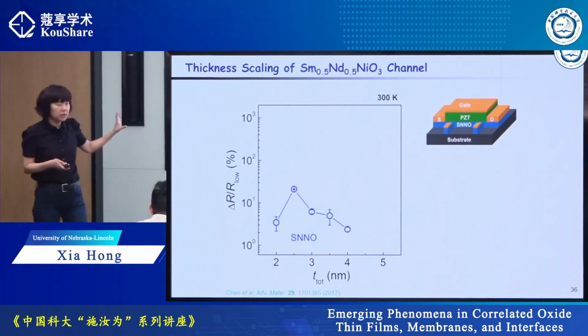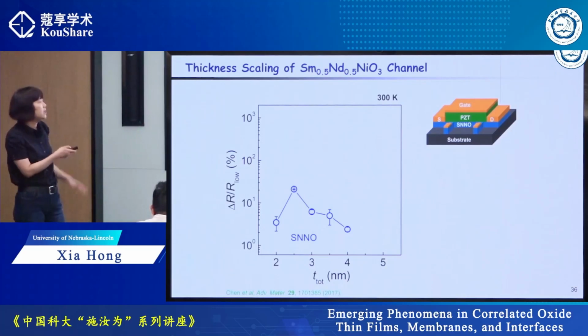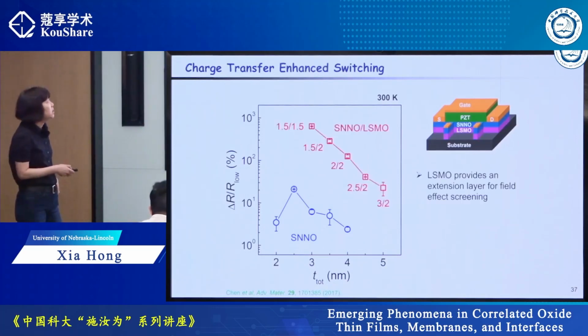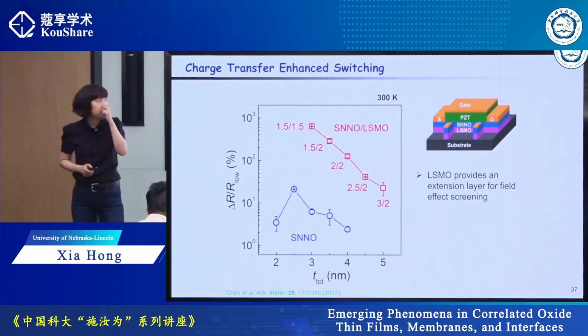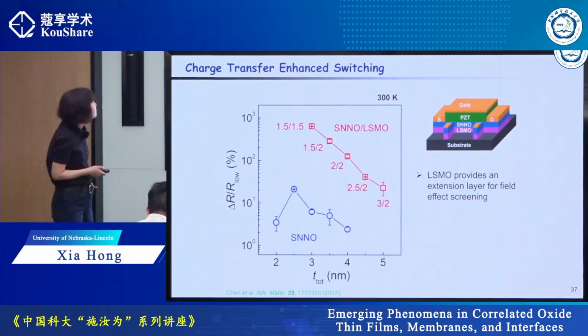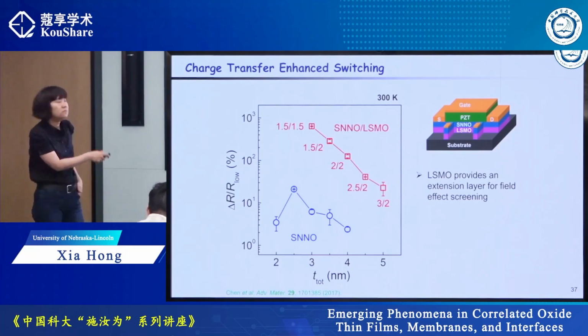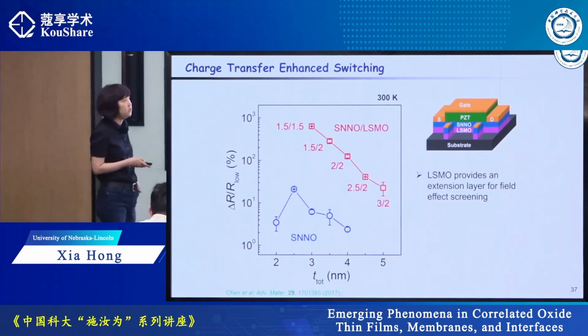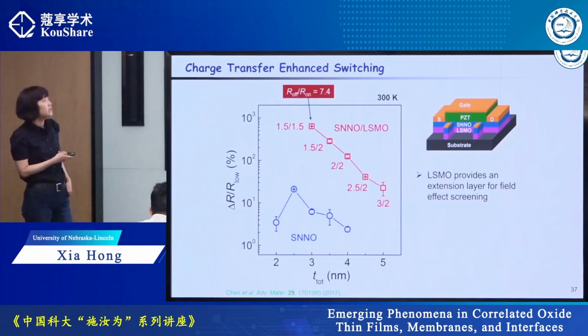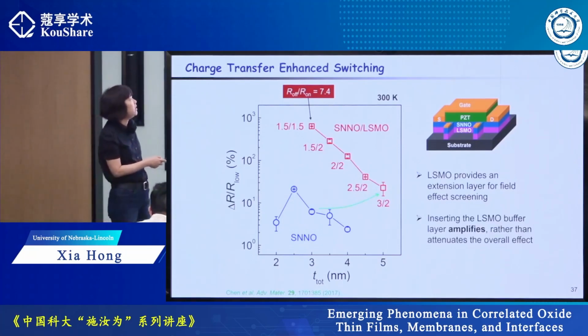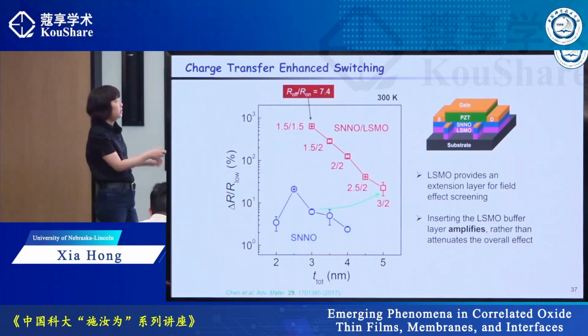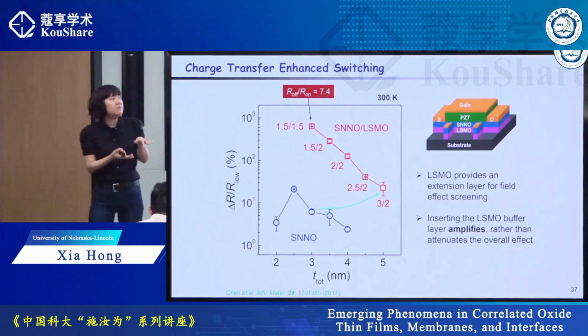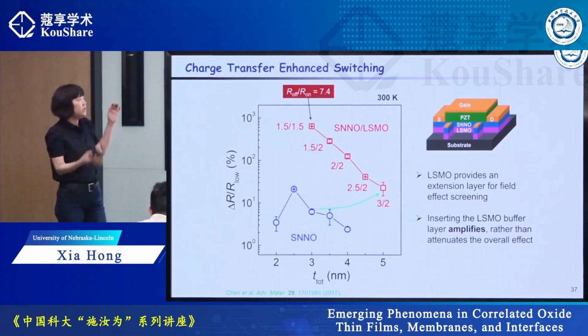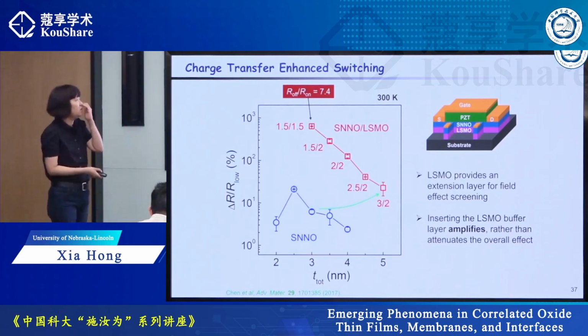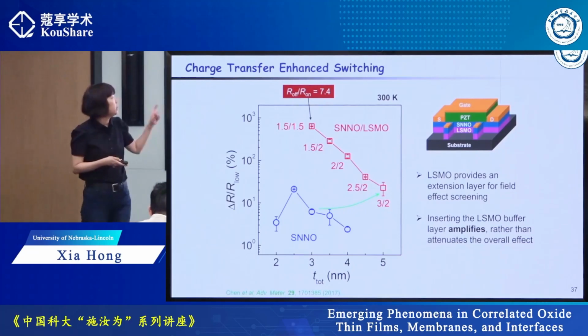Again, we want to learn what the scaling behavior is. This is the scaling behavior for single layer SNO, and this is the scaling behavior for the bilayer channel. There are a couple of things I want to point out. The first thing is that for the same channel thickness, we have more than 2 orders of magnitude enhanced resistance switching ratio. The highest ratio for SNO bilayer is 7.4. What is interesting is that if I have a 3 unit cell SNO and insert an additional buffer layer, you would think that with a thicker channel the effect should be smaller, but actually the effect is larger.